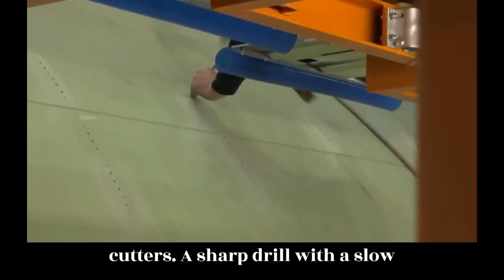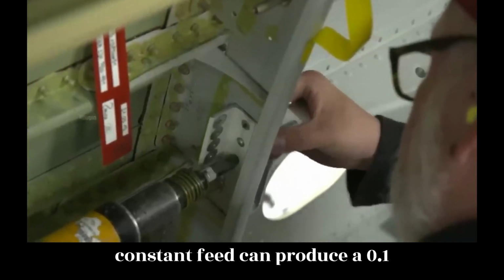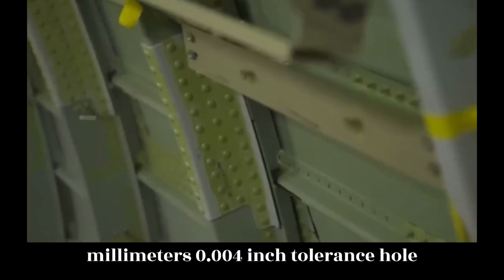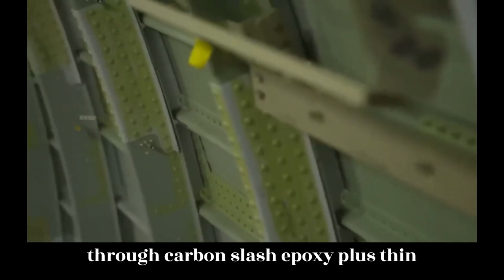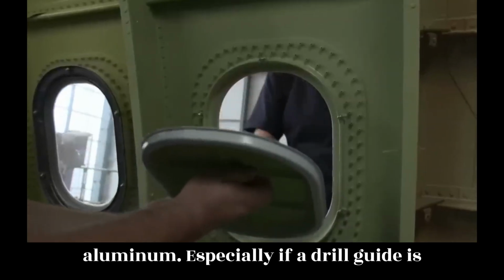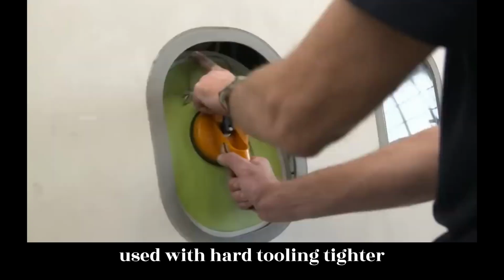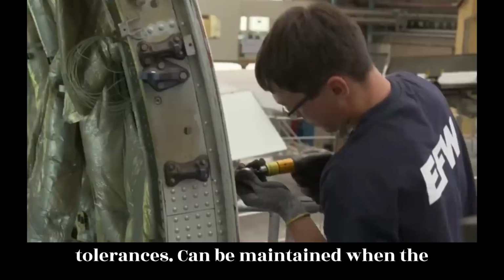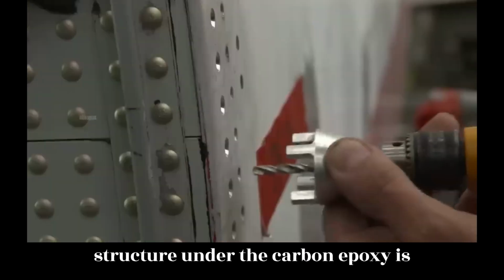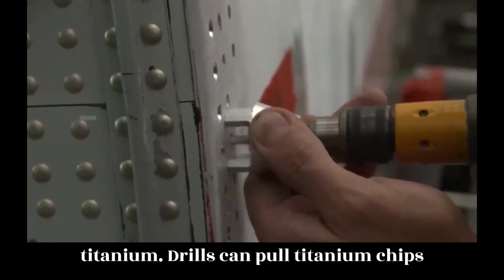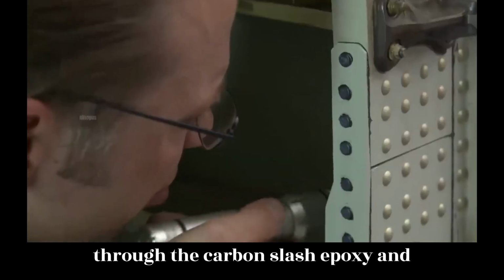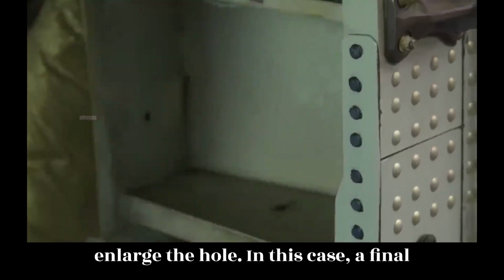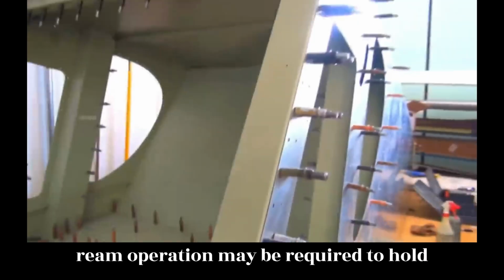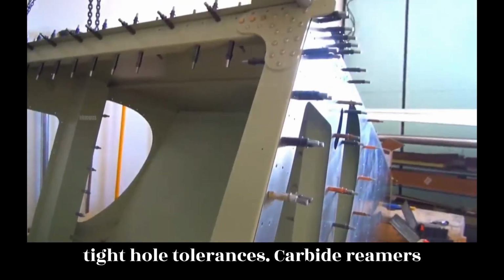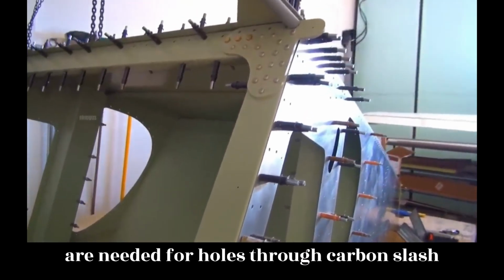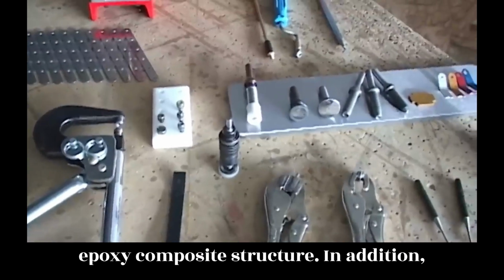A sharp drill with a slow constant feed can produce a 0.1 mm, 0.004 inch, tolerance hole through carbon/epoxy plus thin aluminum, especially if a drill guide is used. With hard tooling, tighter tolerances can be maintained. When the structure under the carbon/epoxy is titanium, drills can pull titanium chips through the carbon/epoxy and enlarge the hole. In this case, a final ream operation may be required to hold tight hole tolerances. Carbide reamers are needed for holes through carbon/epoxy composite structure.